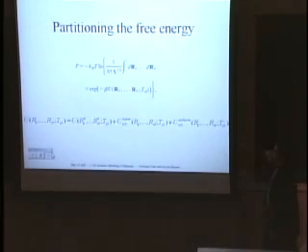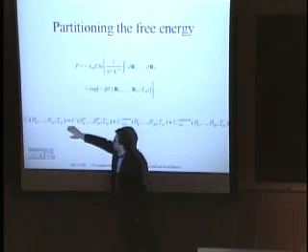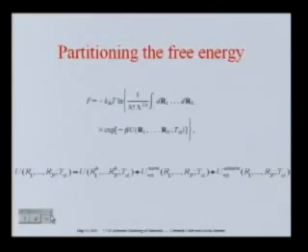I've written here the free energy as the logarithm of the partition function. U will be our internal energy, and this is what you calculate with your quantum mechanical model. For simplicity, I've broken this into 3 parts. I've written out the energy at equilibrium, and then the energy for any possible configuration of the ions can be written as the energy at equilibrium plus what is called the harmonic term.